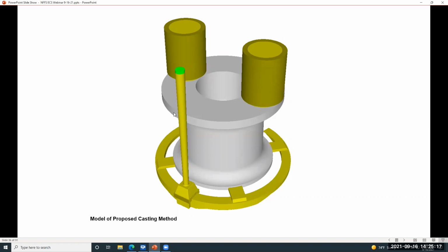Also notice that we have a green disc on the top of the sprue. That's called fill material. That allows us to run a filling simulation that essentially becomes the source of hot metal into the system. And also, we have a filter down here. SOLIDcast has a utility that will allow you to create ceramic filters. And we actually modeled the flow down the sprue, through the filter, and through the gating system.